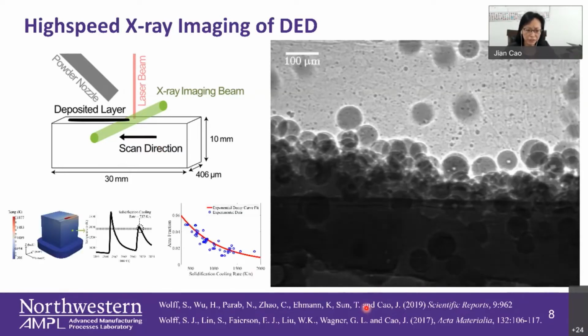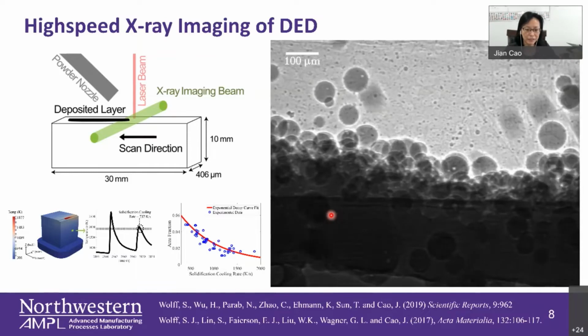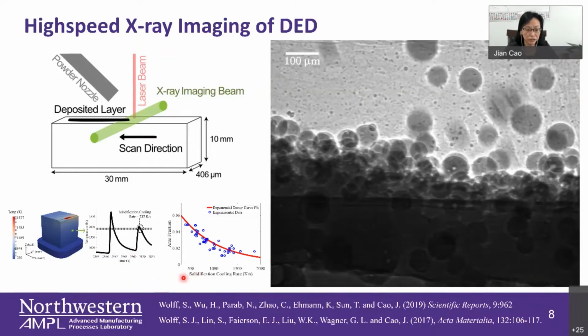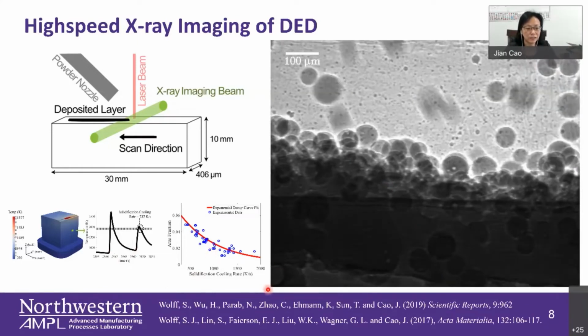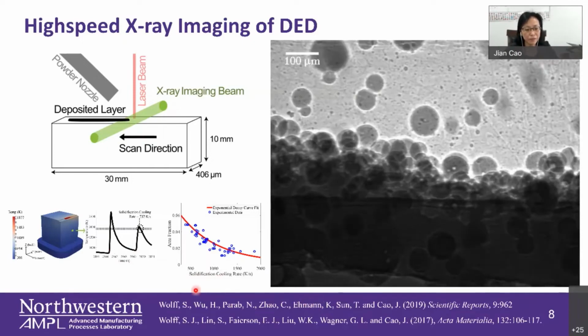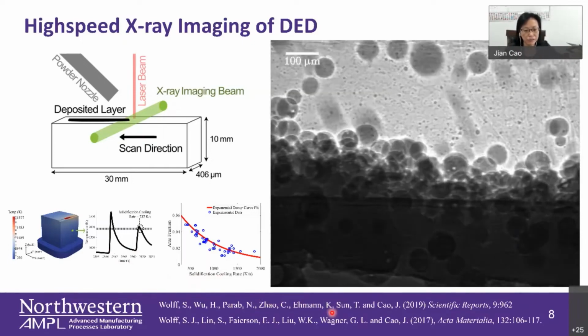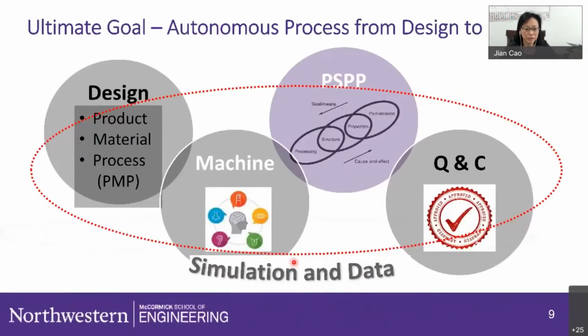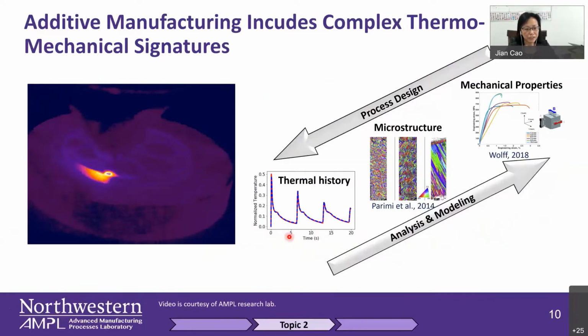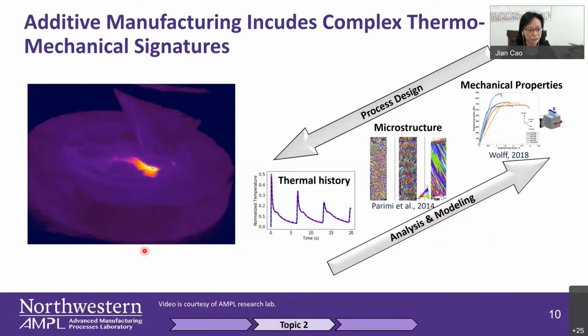So I'm not going to talk too much about this, but the key point is that what we have found in the past is that the solidification rate determines the porosity shape distributions quite significantly. So let me talk about the PSPP part. I mentioned the machine. When you look at this one, we know the thermal history really determines the microstructure and therefore determines the mechanical properties. Here you can see our image, we are making what I call a metal wafer. You can see the internal structures right there.